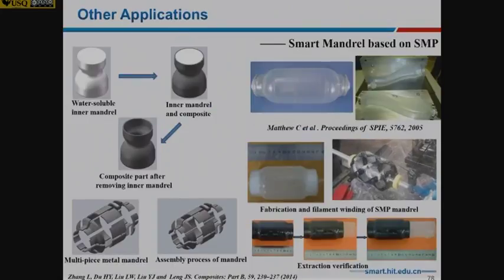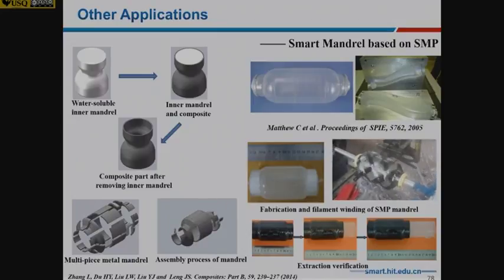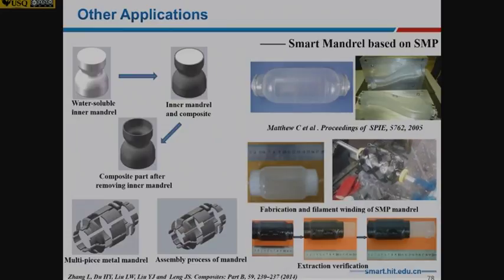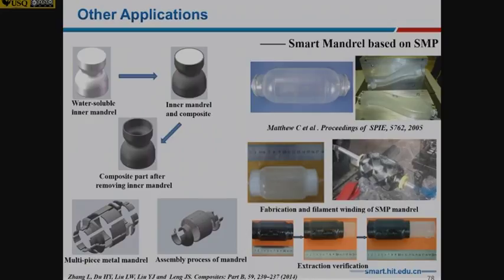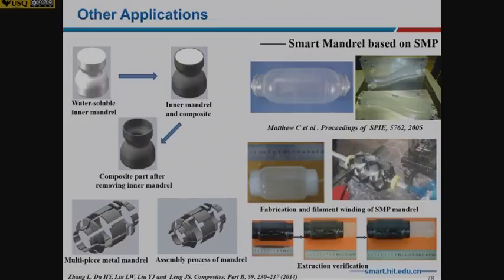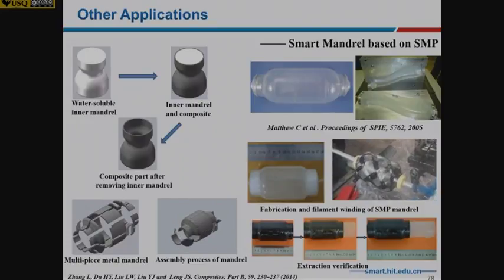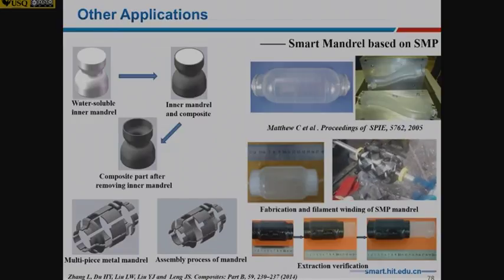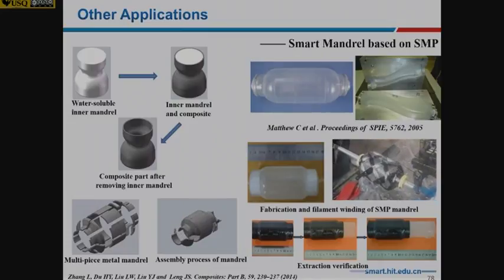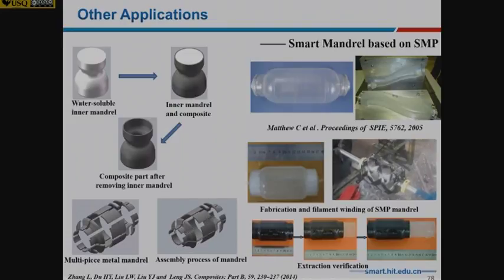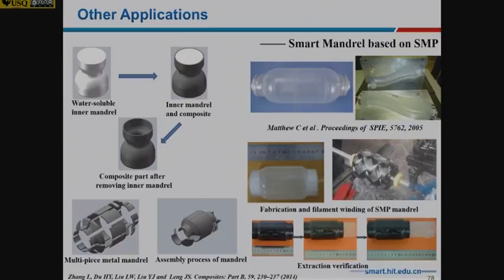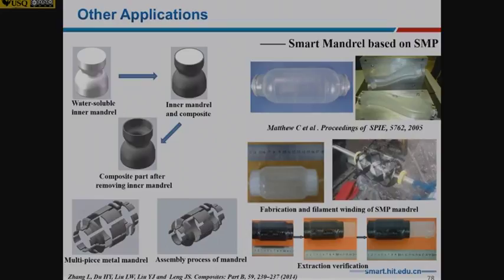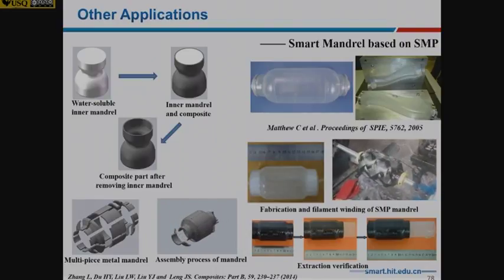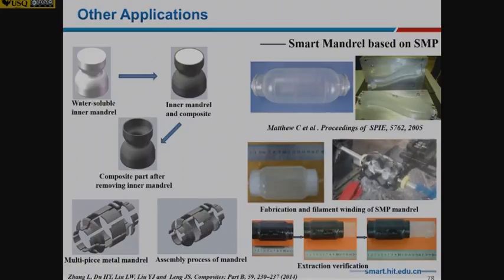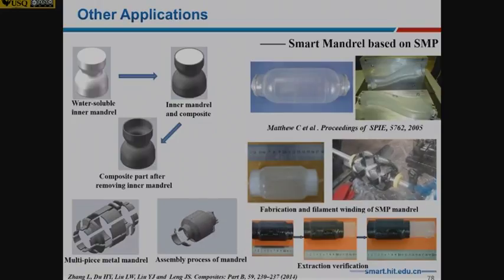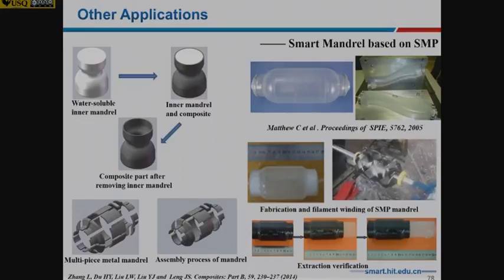So, other applications. The first one I want to point out is the smart mandrel. This one has a lot of applications. Normally, to make composite structures, like pressure vessels and complex structures, when you do filament winding, you have to have some mandrel. But the mandrel you can normally make either as a water soluble mandrel, which can be dissolved by water or different solutions, or you can make some multi-piece metal mandrel, which is assembled and reassembled again, but it's very complex. So the people from the USA, from the company called CRG, made this bottle, and the right hand side is another air inlet. For this one, you can make the composite structures, then you can release it after you do filament winding. And the bottom one is one our student made, doing filament winding with a similar idea, and after that you can release it and take off the mandrel easily.